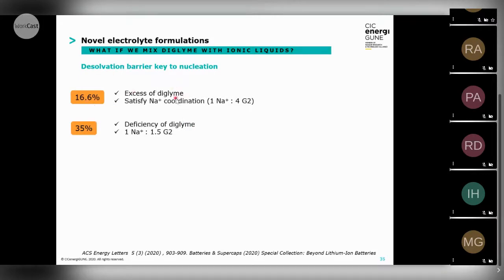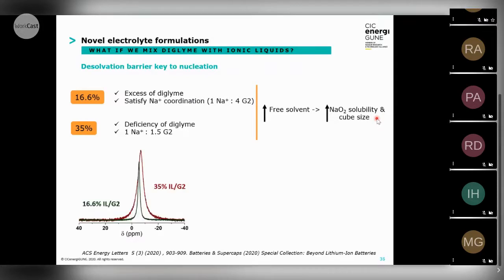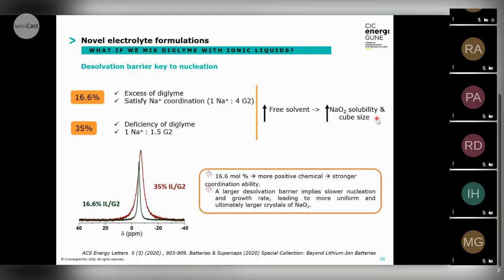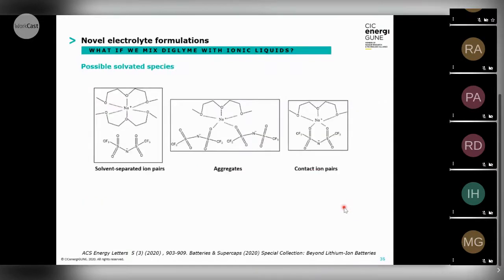So let's explain the different samples. In the case of 16.6, we have an excess of glyme. This is the coordination. And in the case of the high concentration of salt, there is a deficiency of glyme. This means that in the first one, you have free solvent, which is going to increase the solubility of sodium superoxide in solution, and hence the cube size is going to be bigger. Also, when we look at the two solutions, we see a more positive shift in the case of this concentration, meaning a stronger coordination ability. That means a larger desolvation barrier, which implies slower kinetics and leads to more uniform and also larger crystals. That's the reason we saw this difference in the morphology.